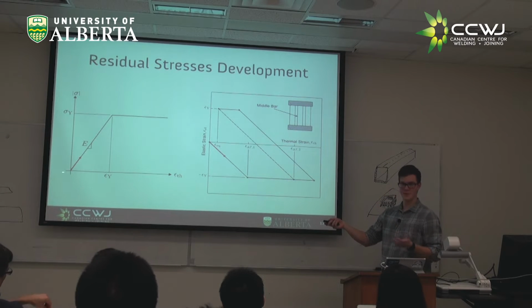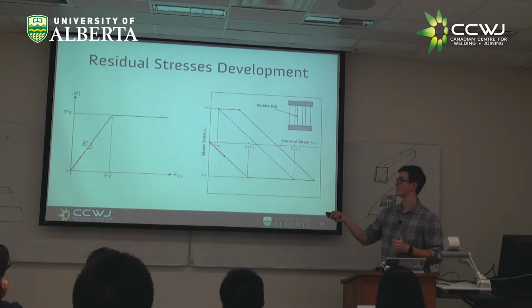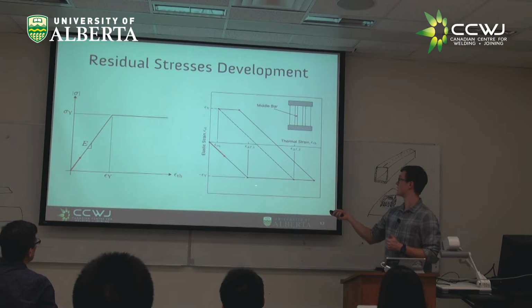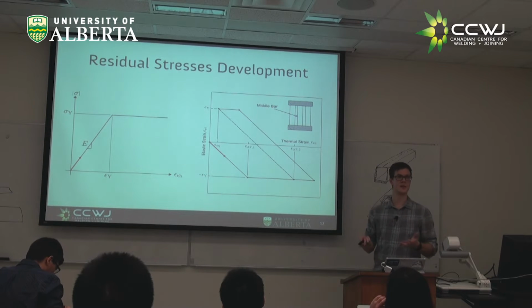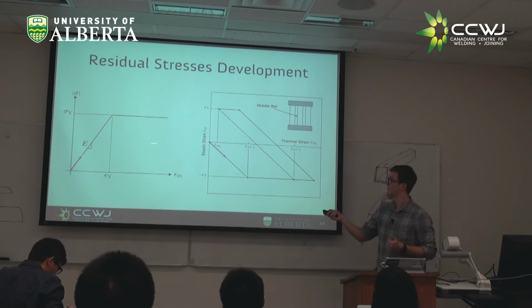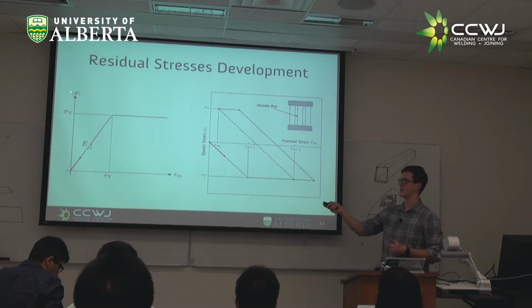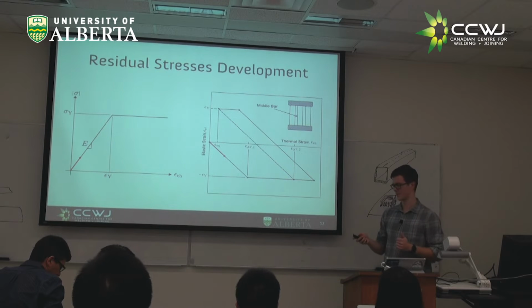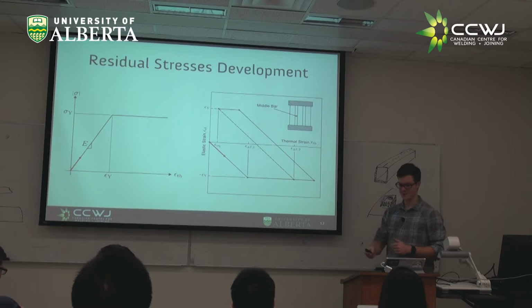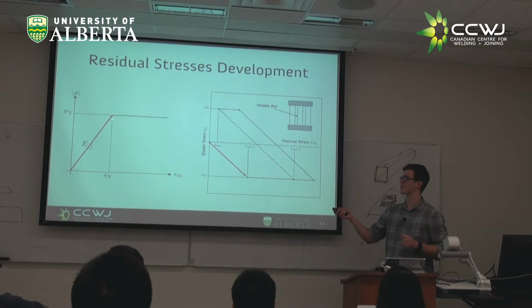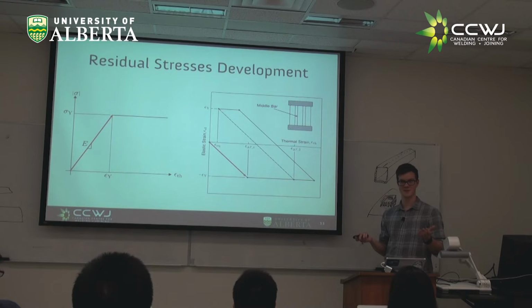So if you imagine we start here with no thermal strain, room temperature, we add a little bit of temperature, a little bit of thermal strain, we're going to develop some compressive stress. So if we look at now a plot of elastic strain versus thermal strain, where elastic strain is, in our case, proportional to our elastic stress. As we move here on our tensile diagram, we've plotted it with absolute value of sigma, because this is typically what you see for compressive stress. It's the exact same, but now we're moving down into the compressive region. Hopefully you're all with me so far. Now, if we imagine we move a little bit further down, at some point in our compressive diagram, we're going to reach the yield stress. At this point, we can imagine we've reached some equivalent strain to that yield stress. We're going to call it the yield strain. Make sense? No questions so far?